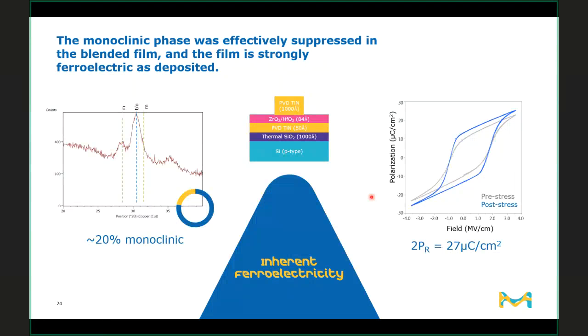And so this is really different than the behavior that we see with the amide precursors that we showed at the very beginning of the presentation, because in that case, you only got the phase that you wanted under certain specific conditions, whereas in this case, presumably because these films are phase stable and because we can apply the top electrode and not have to perform any specific annealing in order to get this film to crystallize in the right phase, you could actually have much more independence about what electrodes you choose, what thermal profiles you choose, and this could be very beneficial overall to the field of depositing ferroelectrics for a variety of different applications.